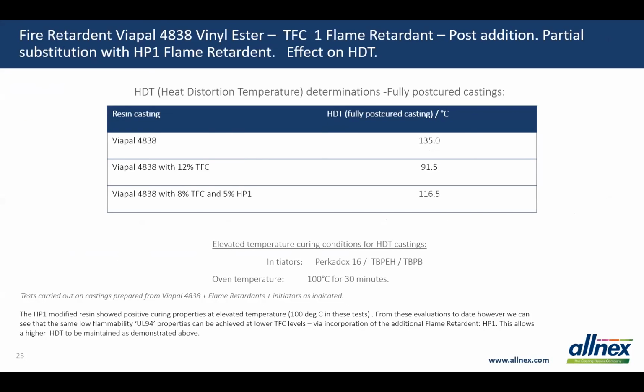Heat distortion temperature, as I mentioned, by incorporating a combination of the two flame retardants, we managed to reduce that plasticizing effect by reducing the amount of TFC, and we brought that HDT back up to a reasonable, about 116 and a half on this test here. The Viapal 4838, this was another test, 130, 135 is typically, each time you do a test, you do another run, obviously, as another control. But it's a lot better than 91.5, or the maximum we could get from the previous test without the modification with the new reactive flame retardant. So we're quite pleased with that one.